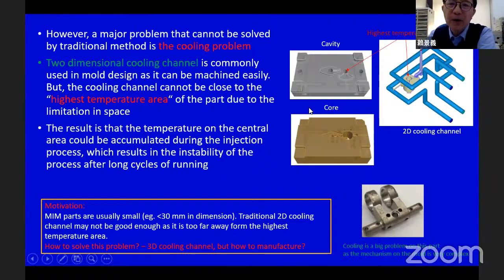Usually, when we design a mold, we use what we call a two-dimensional cooling channel. So this is the two-dimensional cooling channel. The cooling channel is embedded inside the cavity or inside the core. Because this is just two-dimensional, it can be fabricated using a CNC machine. But the problem is that we may have some area where the temperature is very high. We call it the highest temperature area. For example, in this example, this area has a very high temperature.